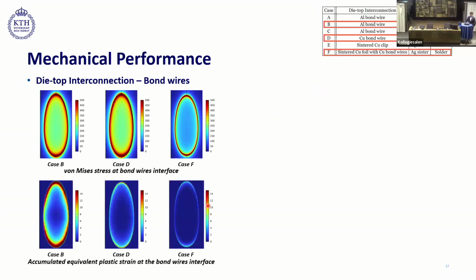Here, we are looking at the accumulated equivalent plastic strain. So this is a bit different. It's not viscoplastic, it's plastic. And we see that the plastic strain accumulation in aluminum bond wire is higher than in copper bond wires. And that's because the yield strength of aluminum is lower than the yield strength of copper. In case F, we see that it's minimum.